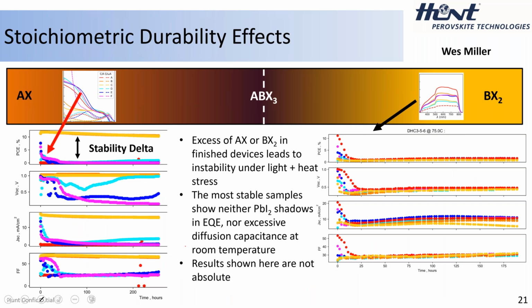So how does this reflect on durability? That's the big question. There's been papers published that show that maybe a little bit of extra lead iodide, you kind of overbake your film, you form this lead iodide shell, and it improves your durability. This is an older thought. I don't know if this really persists as much in academic circles, but it's clear here on the right, if you do have too much lead iodide,